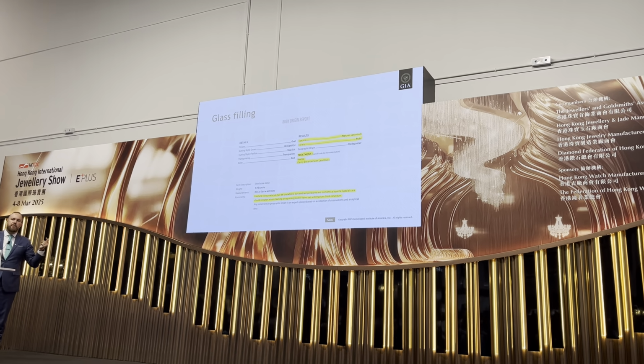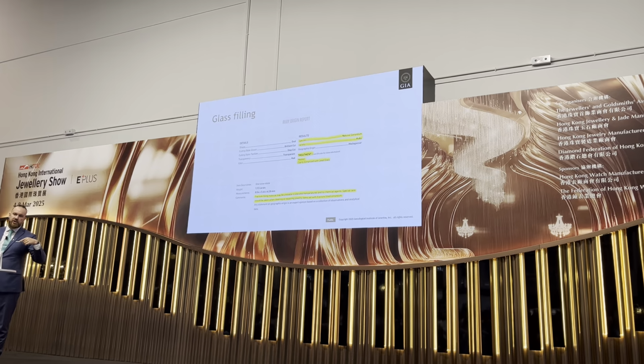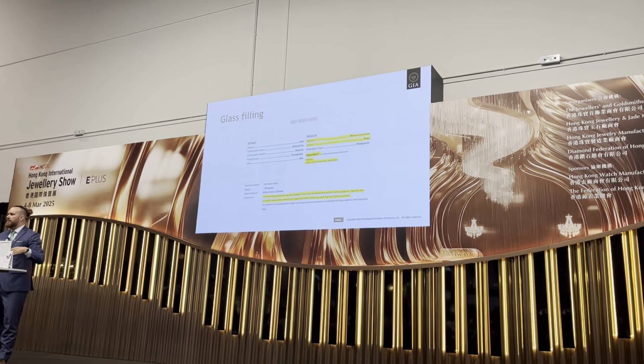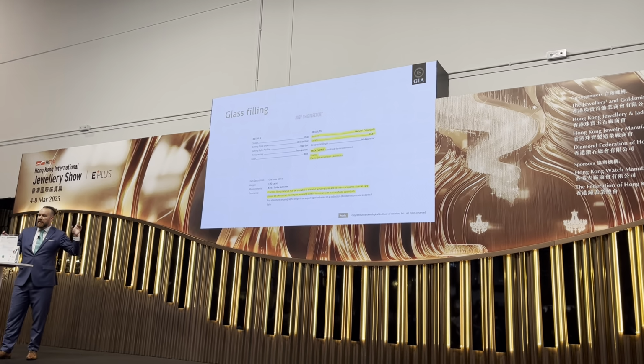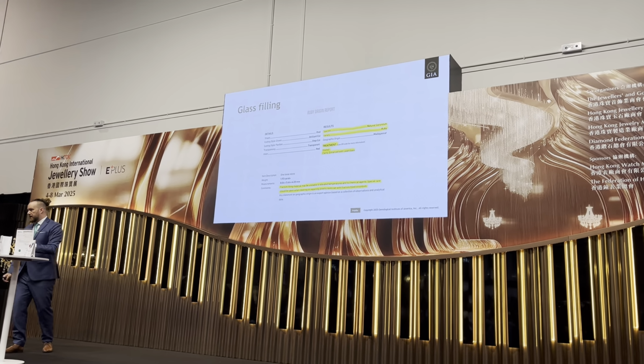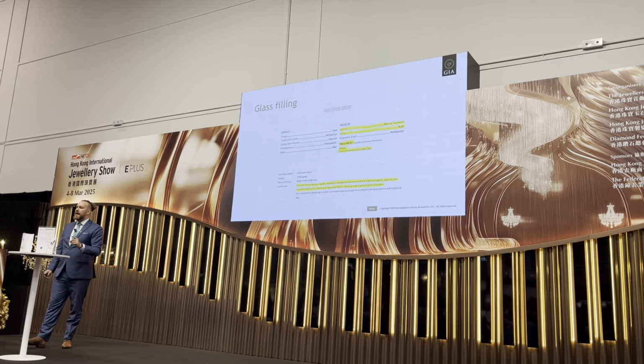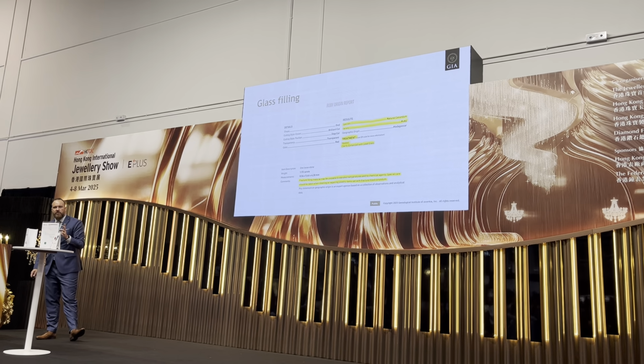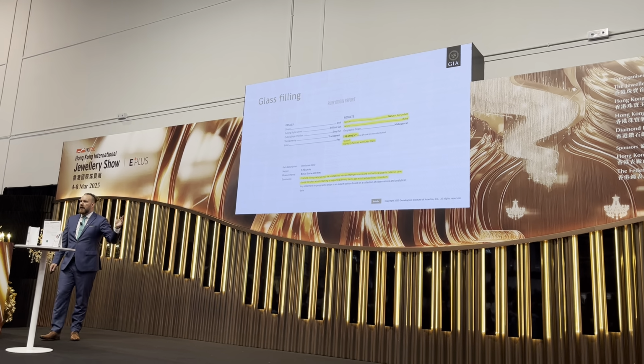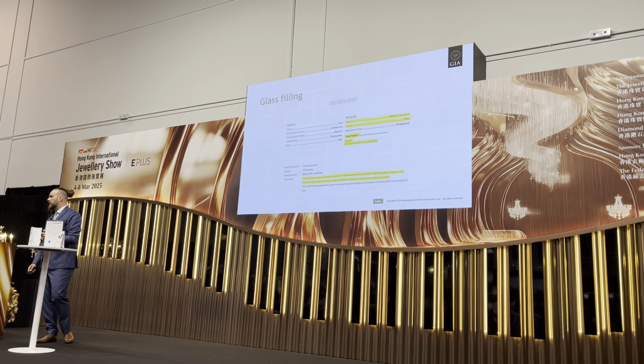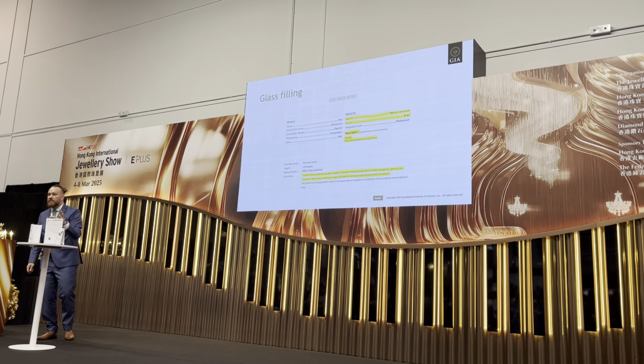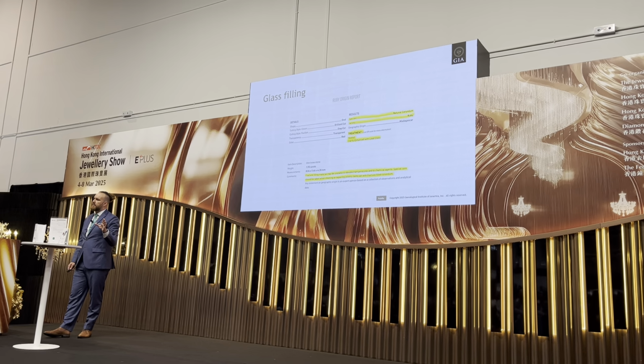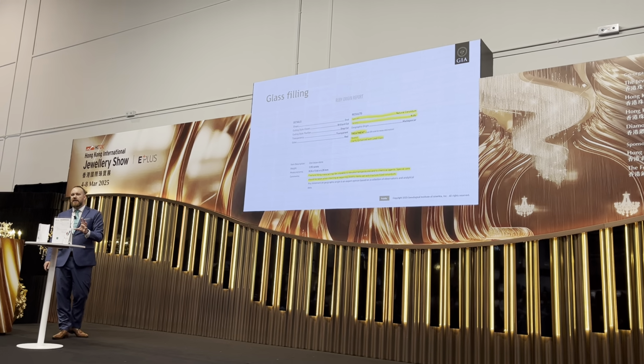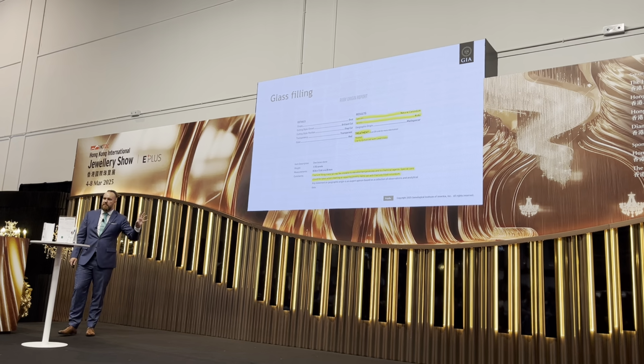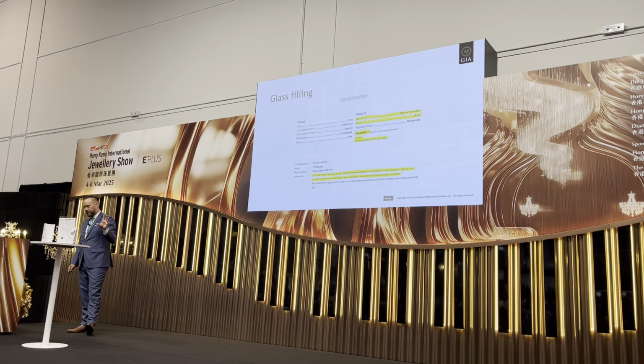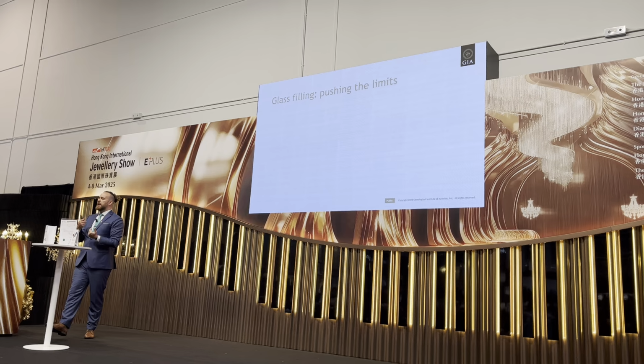Because for example, if you put a stone like this to the jeweler's torch, a corundum, a ruby or a sapphire does not care. But the glass inside those fractures will care. That will get altered, will even melt and leak out. So it is very important to notice, even as a jeweler. If you put this to aggressive jewelry cleaning products, which would have no effect on your corundum, on your ruby and sapphire, they can have a very big impact on the glass that is used to repair, to clarity enhance these stones.